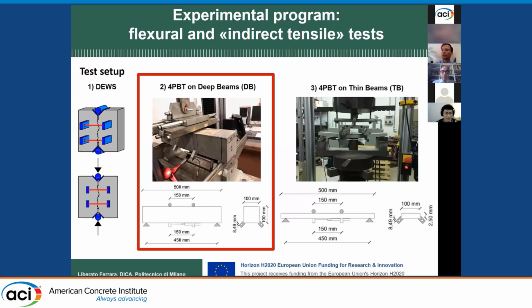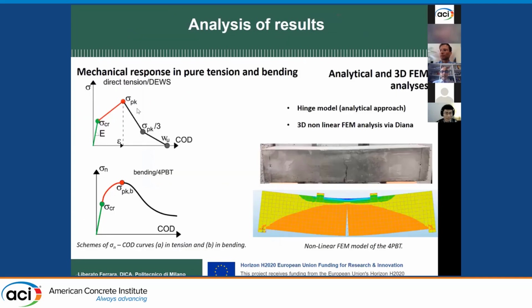And obviously we wanted to compare with the results that you can have from an inverse analysis of the flexural test that you perform on this. So we performed a classical inverse analysis, hypothesizing a constitutive relationship, stress-strain and stress-crack opening after the peak. Obviously, when you convert the crack opening part into a strain, you need the structural characteristic length, which depends on the model that you employ.